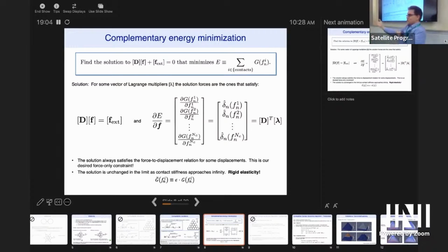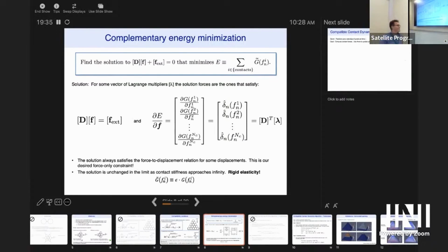So really, I can start with really stiff particles, with stiffness going to infinity, and just divide everything out by 1,000,000,000, and I'll get the same answer. So I can define the scaled complementary energy function just by multiplying the actual one by some small scalar, and just use that instead, so that everything's order 1 in my solver. There's no need for the billion-sized stiffness. I just add a little tilde. Okay, so there you have it. So what I should do, according to this rule, is first find the set of solutions that would satisfy force balance.